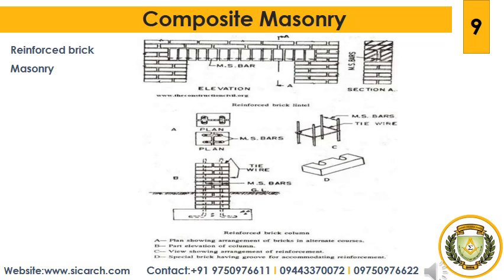The reinforcement should be effectively bedded and surrounded with mortar cover of 15 to 25 mm to protect against corrosion. Reinforced brick masonry is frequently adopted for retaining walls, especially where exposed brickwork is necessary for architectural considerations. Special bricks with grooves accommodate reinforcing bars in cement mortar (1:3), with vertical mild steel rounds placed near each face. Horizontal reinforcement in the form of steel mesh strips is also provided at every third or fourth course.